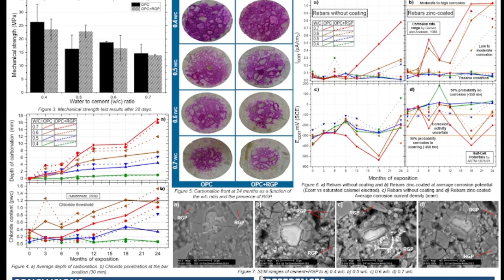Finally, in figure 7, SEM images of cement plus RGP at 0.4 water cement ratio, 0.5, 0.6, and 0.7 show the composition of the 4 water cement ratios with the presence of RGP, and visible in the indicated areas are traces of unreacted RGP particles in the mixtures. This can be identified due to their angular morphology, especially with water to cement ratios 0.6 and 0.7. This ties in with what I explained about the low variability of the mechanical strength in the samples.